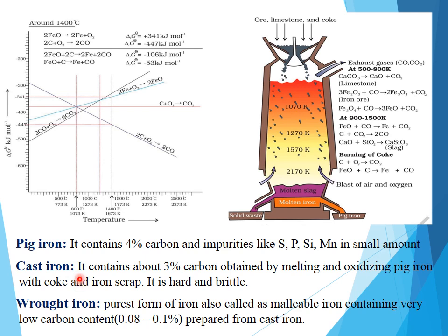And to reduce still further the percentage of carbon, we again carry out the oxidation process by adding coke and iron scrap. At that time you will get the purest form of iron, which is called wrought iron, which is also called malleable iron, which contains around 0.08 to 0.1% of carbon.